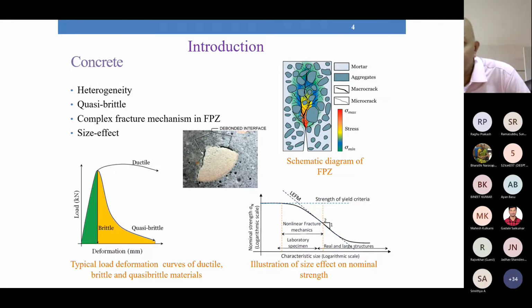This is because in large structures, the size of the process zone is very small when compared to the actual crack size. So it follows the linear elastic fracture mechanics. But when I say large structures, it is as large as dams, where the size of the structure is very massive when we compare it to its constituents, like the aggregate size and so on. Whereas most of the laboratory testing and most of the structures fall in some intermediate group here, intermediate size, wherein neither linear elastic fracture mechanics principles are applicable nor the strength criteria.